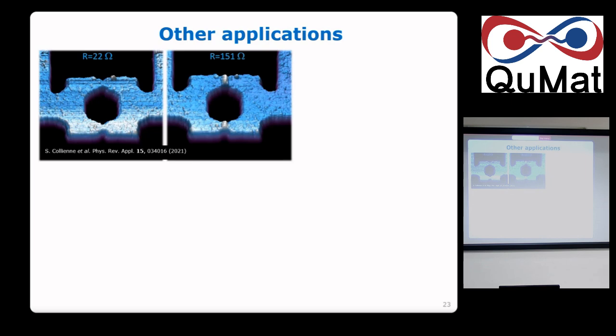We have done that, for example, to modify a superconducting SQUID. So you make a SQUID. This is niobium. You have a junction, typical of a superconducting SQUID in niobium. If the junction is irreversible, the current-voltage characteristic is irreversible and basically useless. So you need to modify the junction, but it is already too small. You cannot do it simply with something. So you just pass big currents, we modify it by electromigration, and you make it work. This is a real application of that.